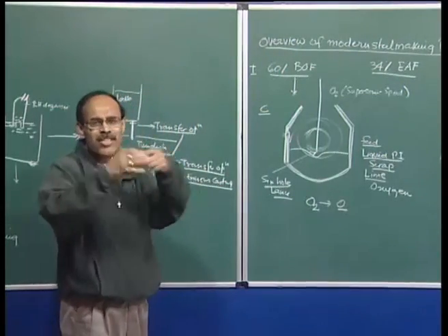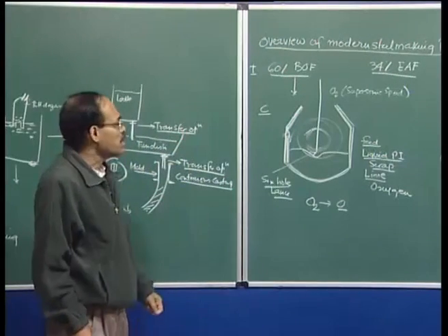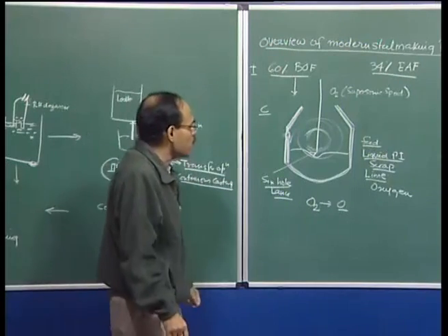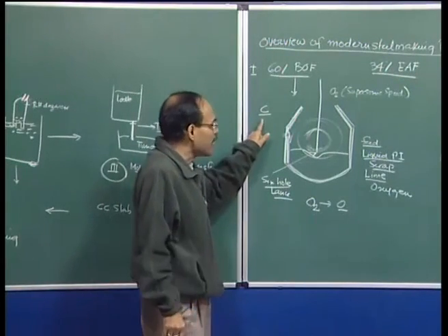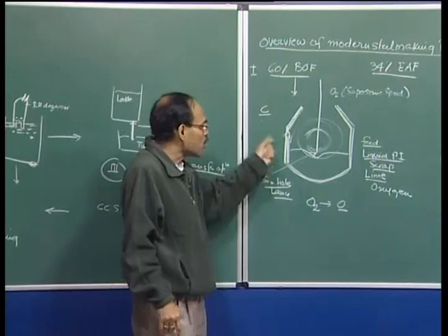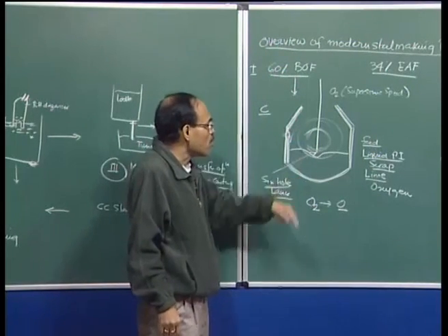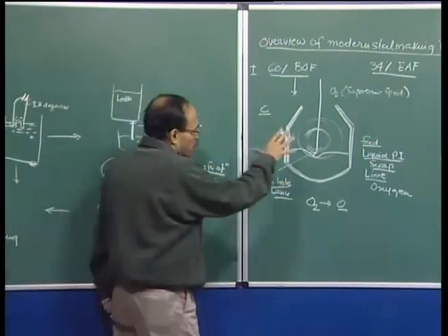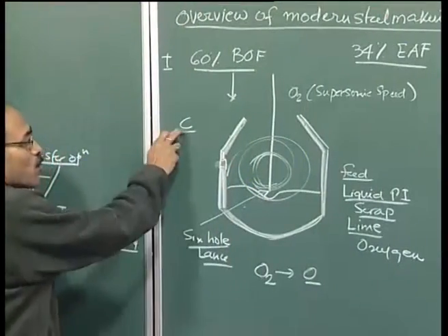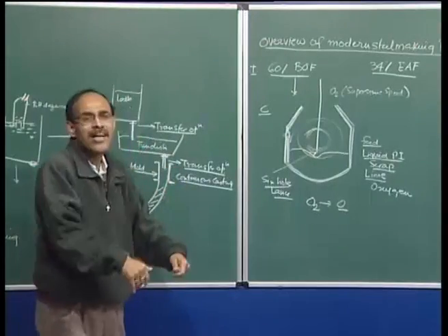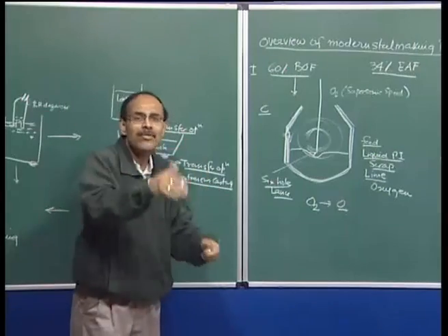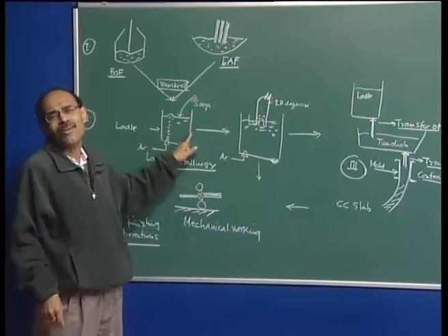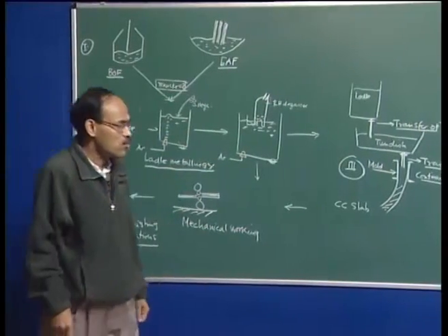Forget about other adjustments like desiliconization. Silicon, of course, will get removed, and dephosphorization and desulfurization to a significant extent. Carbon will be eliminated, phosphorus can also be eliminated, but we will not bother too much about the level of oxygen or sulfur. So, our major thrust in today's primary steel making vessel is decarburization. As soon as the carbon is eliminated, we take the steel to secondary metallurgy steel making processes, and there we adjust other composition, phosphorus, sulfur, etcetera.